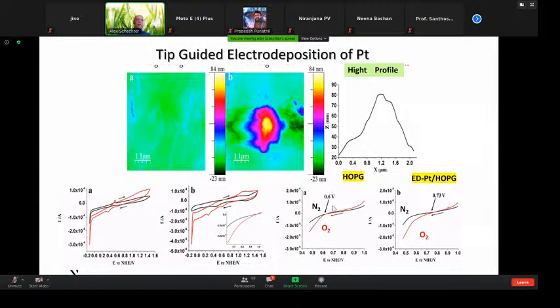So we saw that there is a slight oxygen reduction even on HOPG without having platinum. Now this didn't come as a surprise, because there is a branch in science in this area that deals with non-platinum electrodes that can do oxygen reduction. These materials are based on carbonized materials, different modifications of graphitic structure and non-graphitic structure that allow oxygen reduction. But very little is known about these reactions, despite the fact that we've been studying them for the past 10 years, not just us, all over the world.